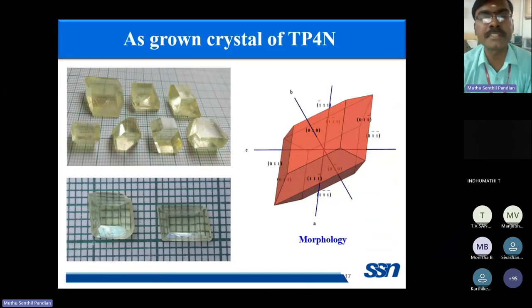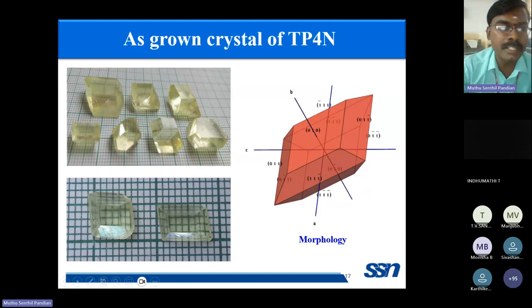These are some of the conventional method grown TP4N, 4-nitrophenol derivative single crystals. So normally in the conventional method, in a beaker, the crystal will be grown like this. From the single crystal X-ray diffraction morphological measurement, we have to identify the morphology of the grown crystal, whether we wish to grow the crystal along its A direction, B direction, C direction, or different planes or different facets. We have to identify this before we go for the bulk growth by the solution method.